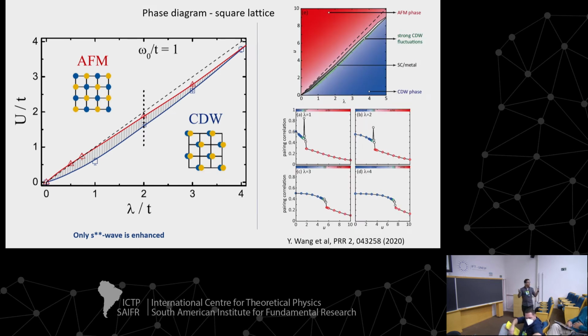And this result, just in parallel with us, some people from Harvard already presented one phase diagram to this model, where they also presented this very similar, but this is not quantum Monte Carlo, they performing some kind of Langevin transformation using a cluster, a kind of cluster mean field, something like it. But the phase diagram is quite similar, but the difference that in the middle here, they present a D wave, not a S wave. So we differ about this. But I will not complain because we cannot present our result so precisely, so there's no problem with it. I believe on that. It can be D wave. So this is our first result.